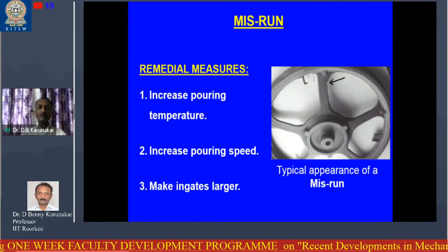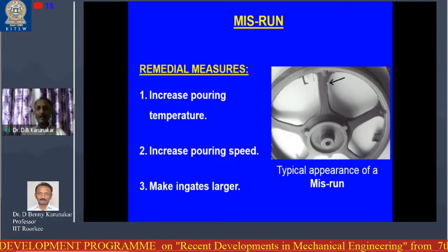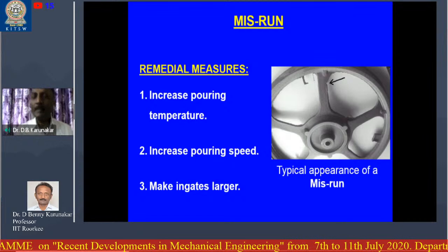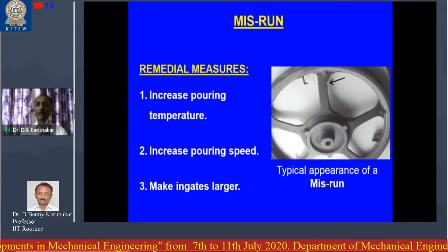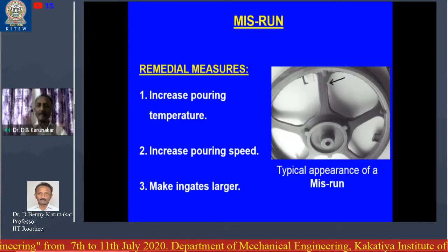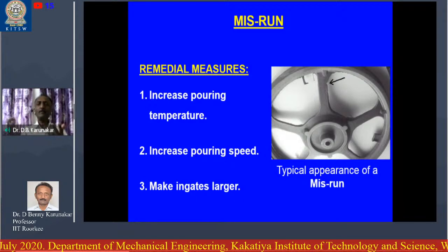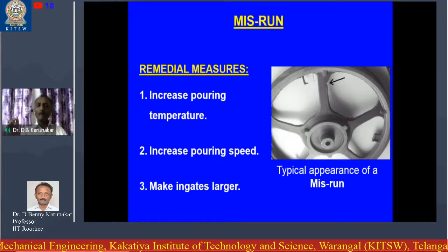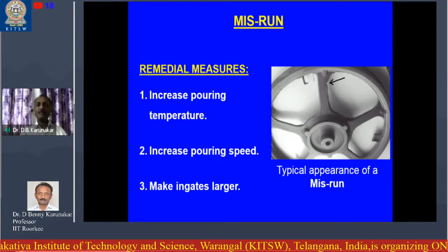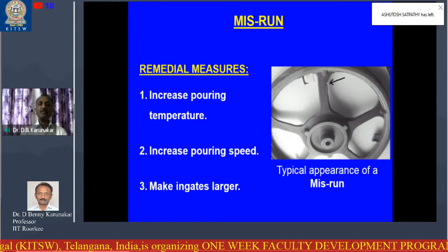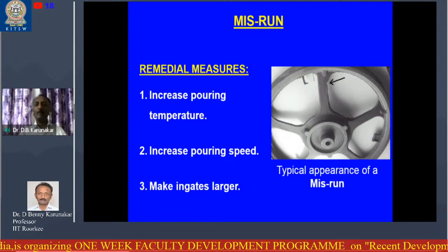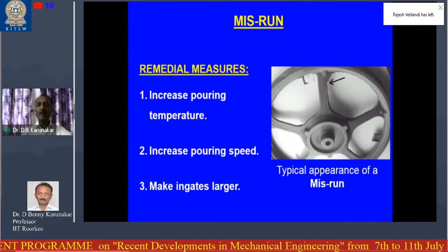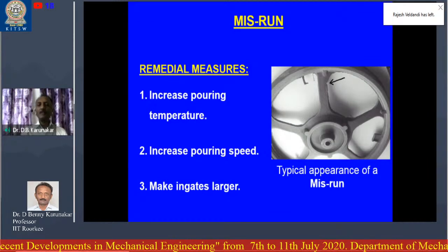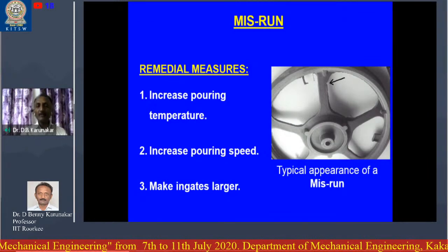Now what are the remedial measures? Increase the pouring temperature. Remember, in casting we come across two temperatures. One is the melting temperature and the other is the pouring temperature. Melting temperature is just enough to melt the metal. If you melt aluminum, at 660 degrees centigrade it starts melting. But that is not enough to pour. If you start tapping at 660, the moment you tap, it solidifies. So it should be at a higher temperature so that you can carry it to the mold and pour. That higher temperature is the pouring temperature, maybe 725 or 750 degrees.